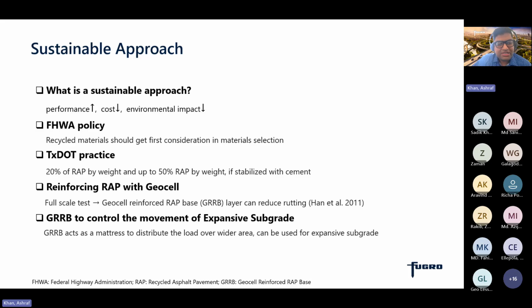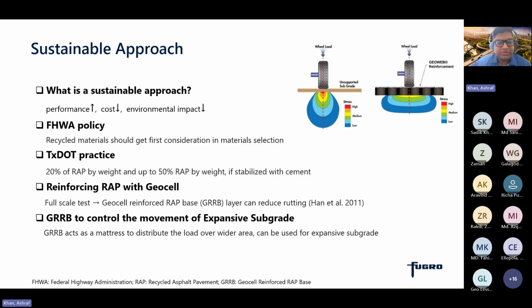So as you see, Professor Han from Kansas State University did some research with Geocell reinforced RAP base layer, and they found use of Geocell reinforcement can restrict the movement and reduce the permanent deformation. This is the first time they were able to use 100% RAP for the base layer, and they proved it with accelerated pavement load testing.